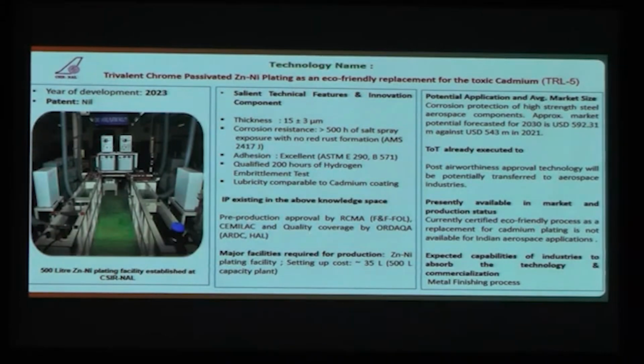We have obtained the pre-production approval from RCMA, CEMILAC, very recently, and we are going up for the next step, the airworthiness certification, maybe within 6 months or so we'll be getting that approval. The costing is at par with cadmium even for this zinc-nickel. And wherever high-strength steels are used, we can use this for corrosion protection as a replacement for cadmium. And post airworthiness approval, the technology will potentially be transferred to the aerospace industry.